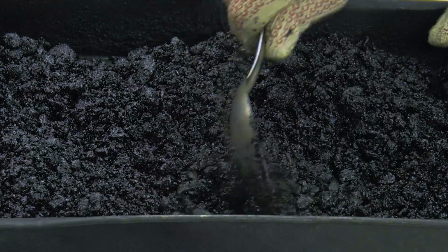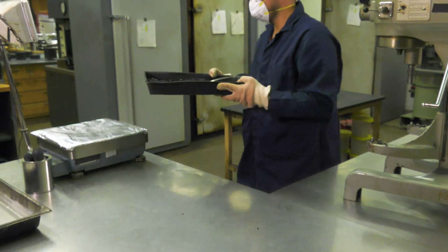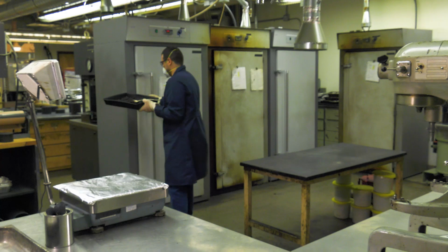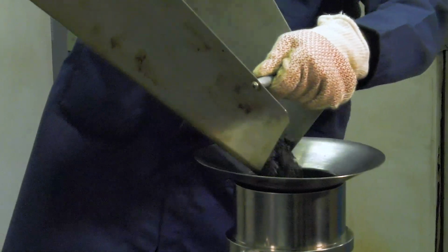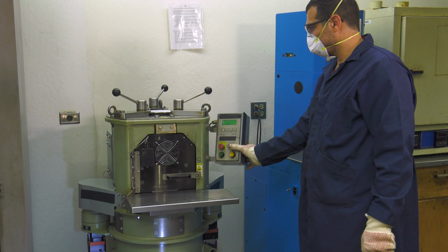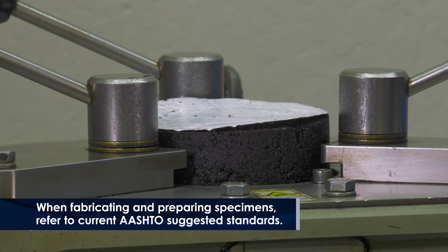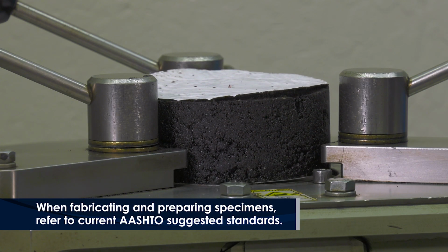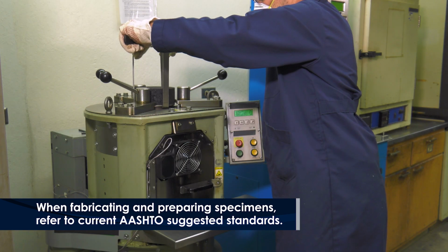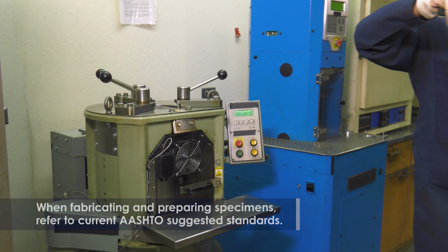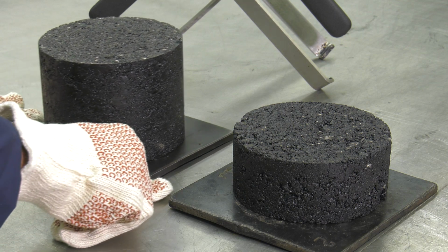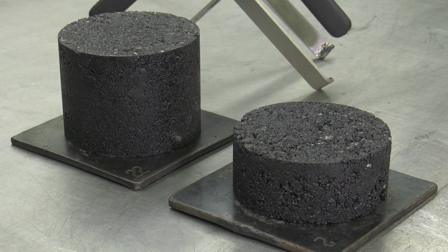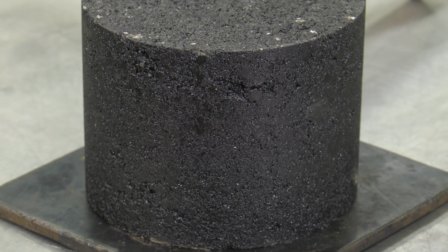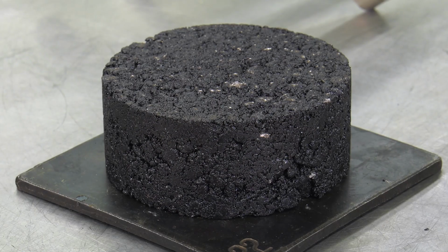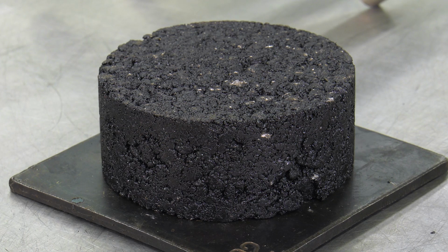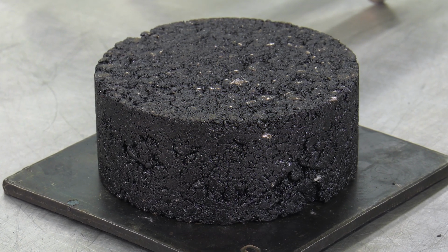For laboratory-prepared asphalt mixtures, prepare and short-term oven condition the mixture according to AASHTO R30. Compact 4 150 mm diameter samples to a target height and air void content using a Superpave gyratory compactor, or SGC, as suggested in AASHTO T312. Specimen thickness should be at least twice the nominal maximum aggregate size, generally yielding a specimen 38 to 100 mm thick. Allow compacted specimens to cool on a clean, flat surface until cool to the touch.